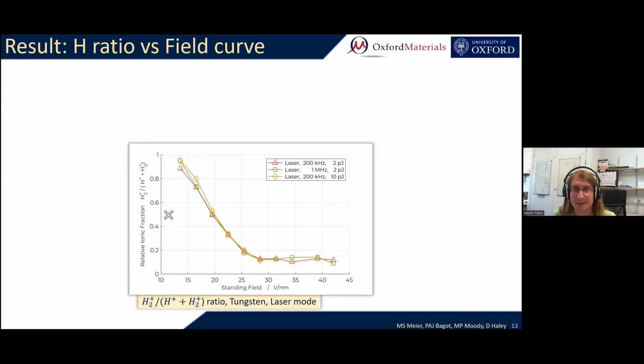And you immediately see that these 3 lines, they overlay pretty much perfectly. And this is telling us that within the range we've tested, the pulse frequency or the laser energy has basically 0 influence on the appearance of our hydrogen peaks. The relevant parameter that we need to keep an eye on really very much is the standing electric field, which we have on the x-axis in the diagram here.